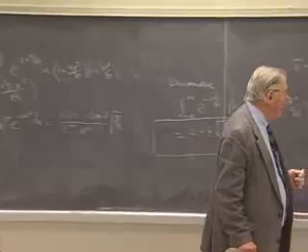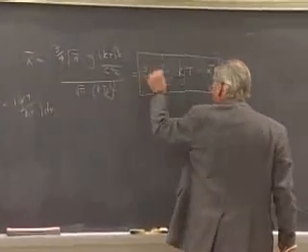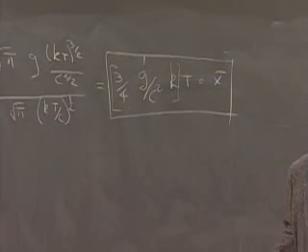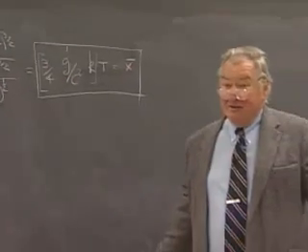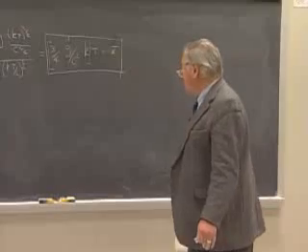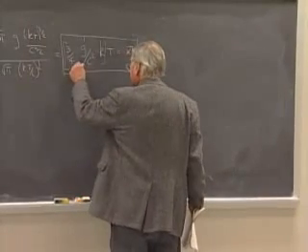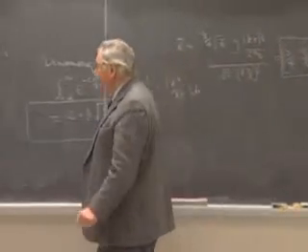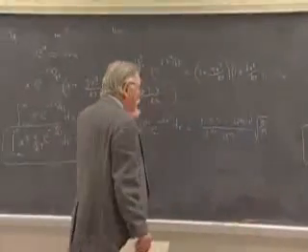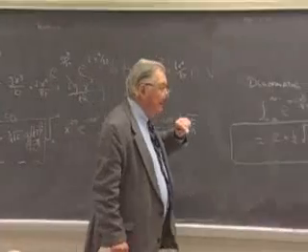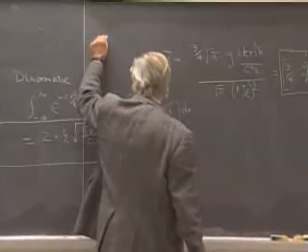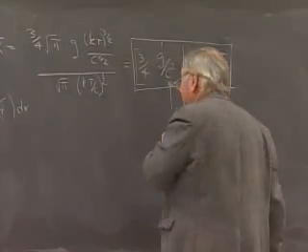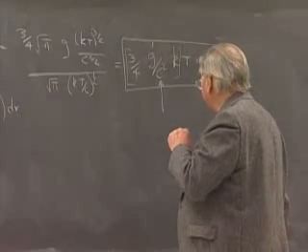The first thing that is very gratifying is that the bond length, according to the simple model, should increase linearly with temperature. So it tells us we would expect things to expand linearly with temperature, which corresponds to reality. The next thing we'll see is that the amount of expansion goes inversely as the square. That's a strong dependence, inversely as the square of the parabolic part of our potential. The c was the coefficient in front of cx squared in our potential. So the stronger the bond, the smaller the thermal expansion coefficient is in proportion to the reciprocal of the square of that term.